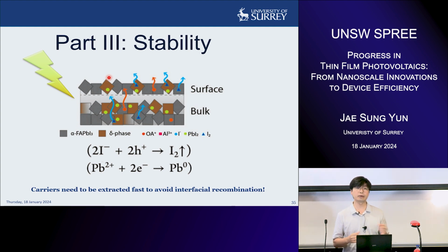In halide perovskites, there are many different mechanisms under the light illumination. Here I want to point out that there are two main effects related to carrier generation and degradation. So your hole will be merged with the iodine vacancies, and these species form and eventually evaporate. And if your material evaporates, escapes out of your material, the structure will eventually collapse. And electrons will interact with lead and form lead zero, and this is going to make a very detrimental effect for recombination.